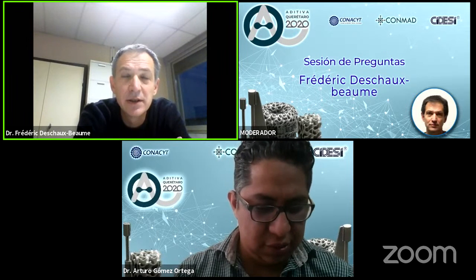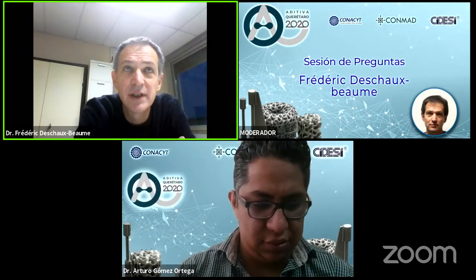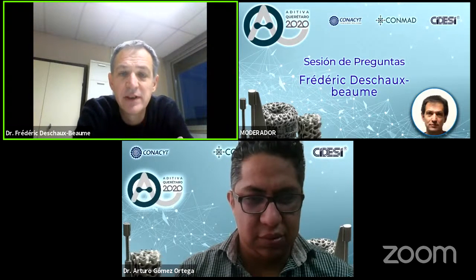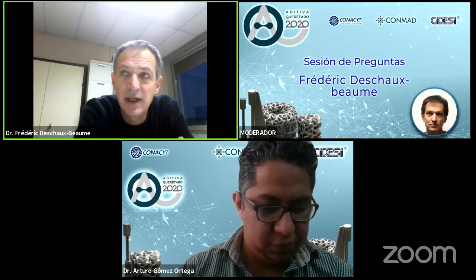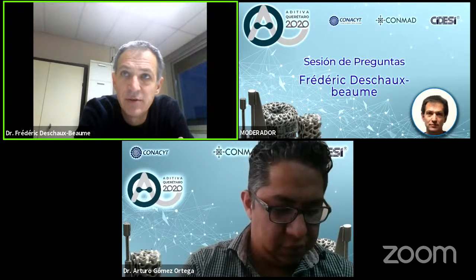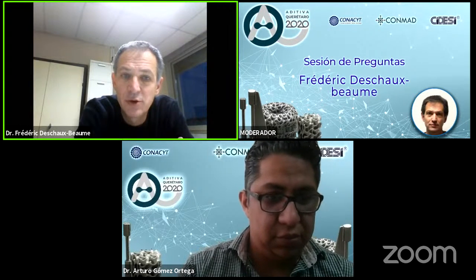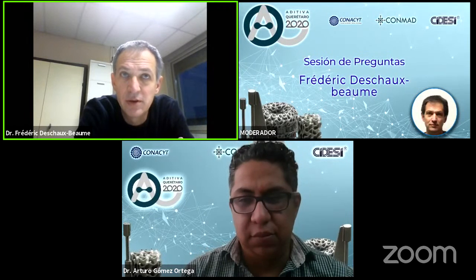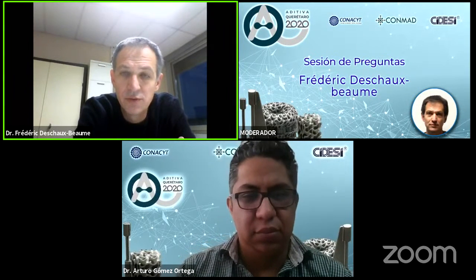Oh, we have the supports are not necessary with this process. The layers are added without supports. We have just a plate, a substrate plate. It's a plate with a high thickness of about 5 to 10 millimeters, and then there are no supports. The layers are deposited without any other supports. The piece can rotate to facilitate the deposit for each new layer, but there is no support.